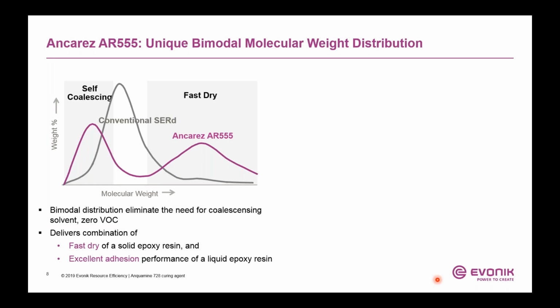So since, as I mentioned in these slides, we use solid resin dispersion AR555. So why? What's special about AR555? Compared to the conventional resin dispersion, AR555 actually has a bimodal molecular weight distribution. So it has a low molecular weight portion and a high molecular weight portion. The low molecular weight portion provides self-coalescence.